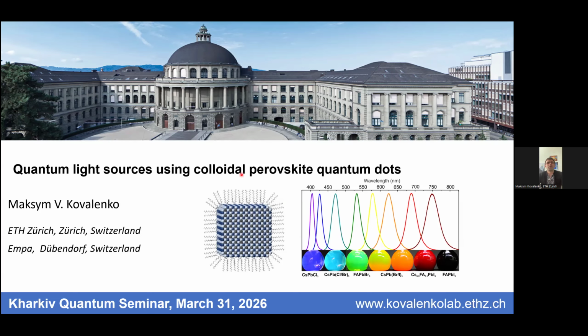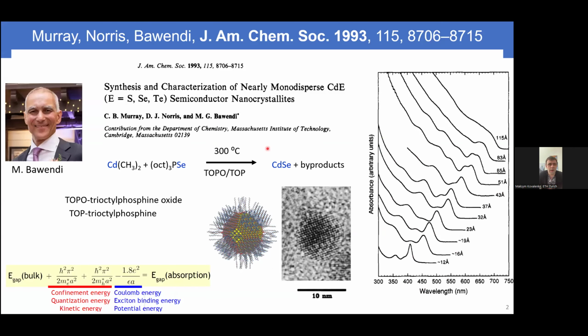But of course, I cannot resist first introducing the big motivation for us for many years. This was the discovery of colloidal quantum dots of conventional semiconductors in the early 80s, and then chemical methods for producing highly precisely engineered quantum dots in the early 90s. One of the three Nobel Prize winners in 2023 in chemistry was Moungi Bawendi, who introduced these colloidal dots. And just to emphasize what colloidal means: they are produced in a solvent dispersion, and they are often handled in that dispersion. To attain that, you have to put a layer of organic molecules around them. So it's always a hybrid organic-inorganic entity.